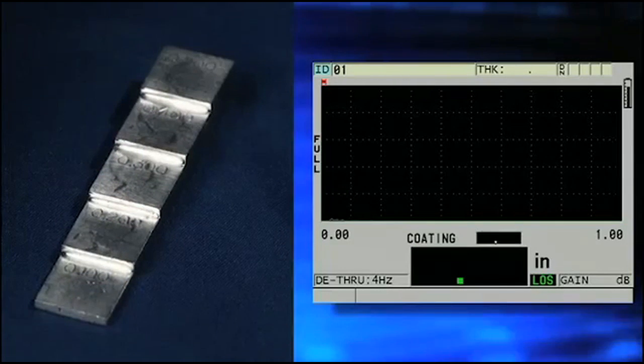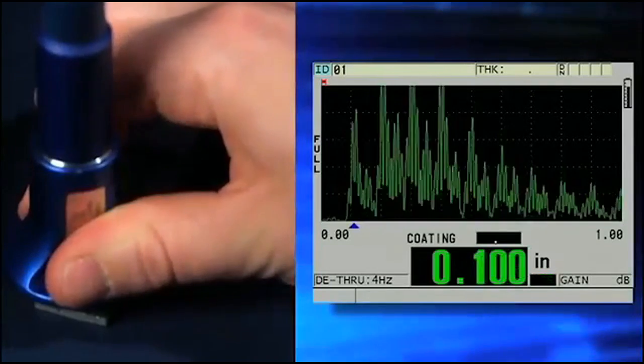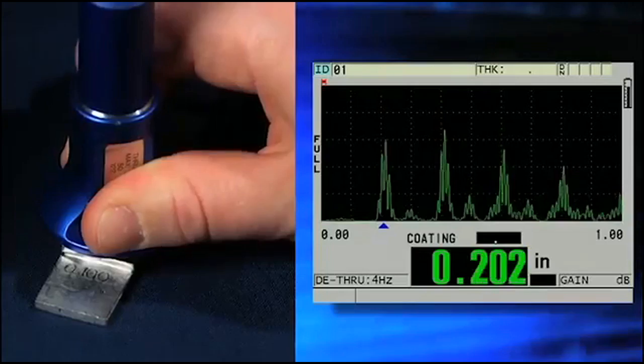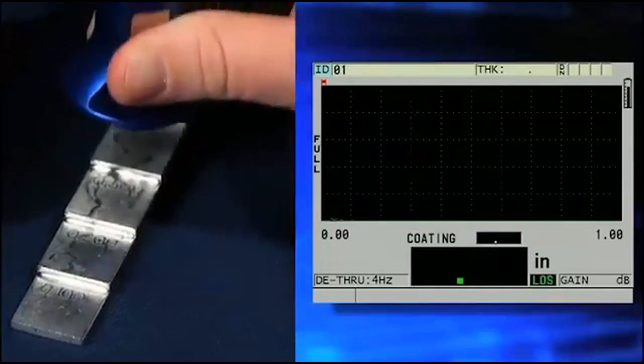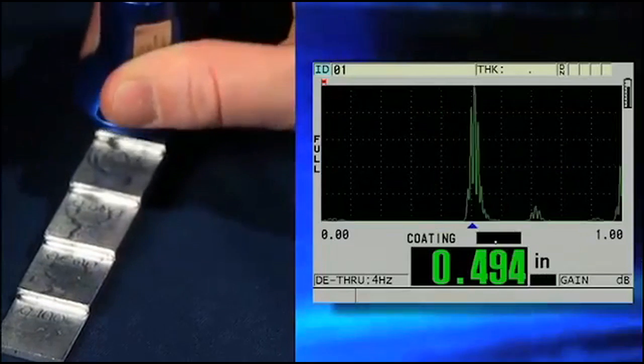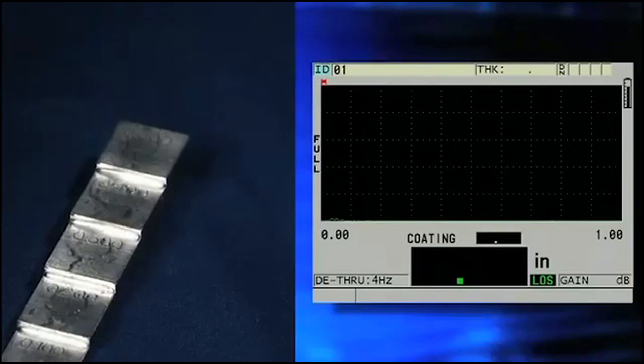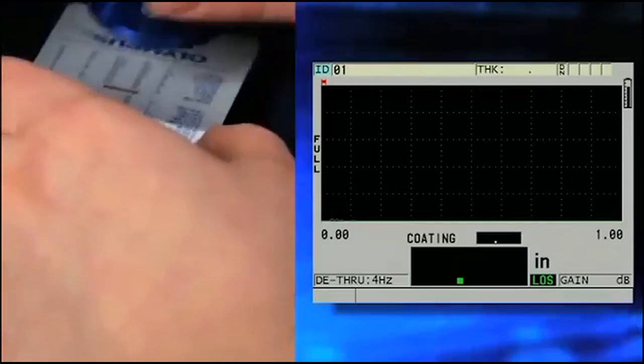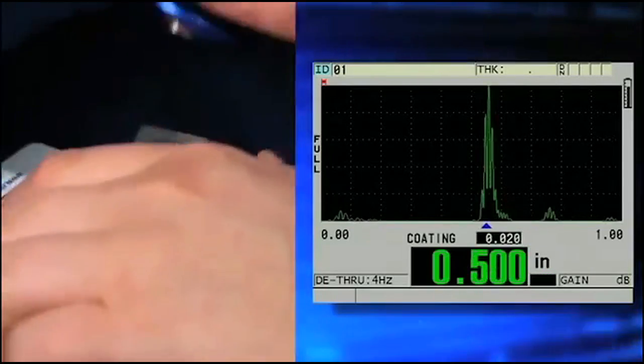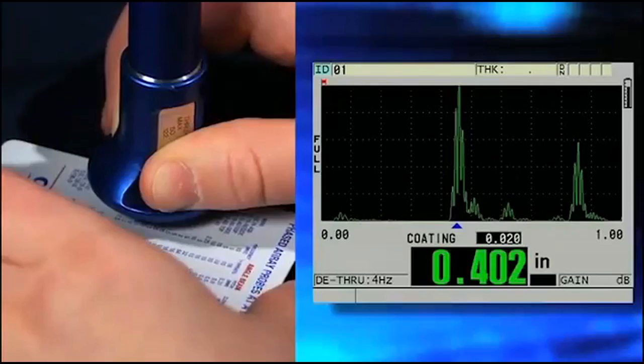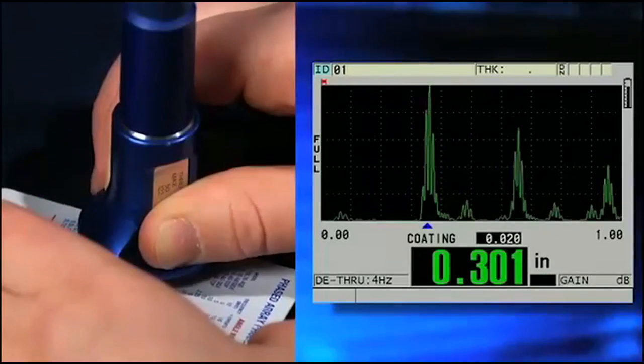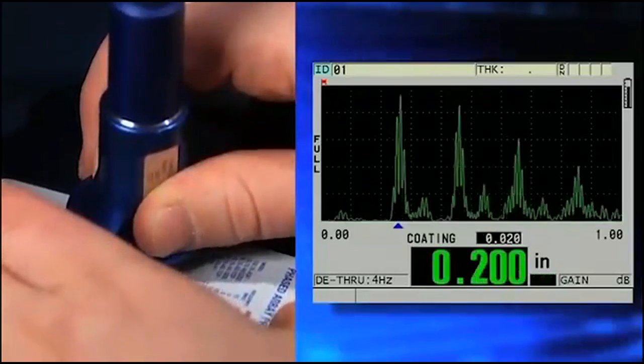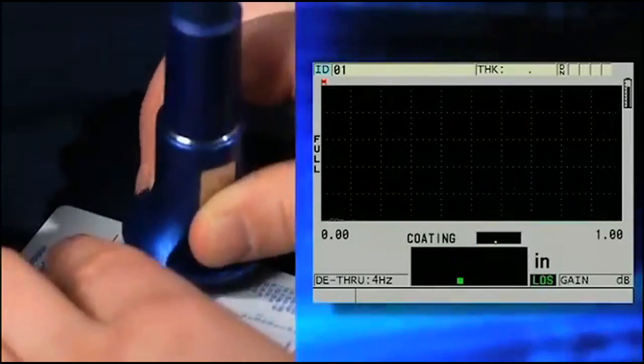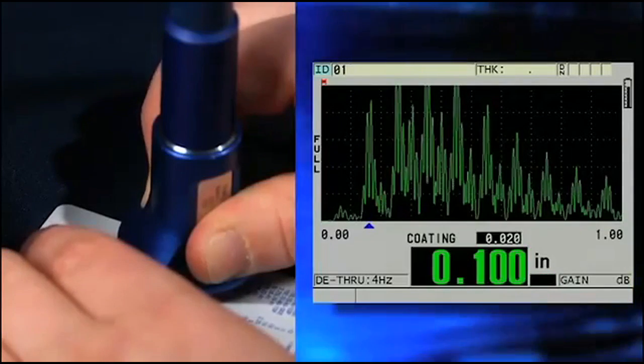We can now go back to the calibration block and check the reference steps: 100 thousandths, 200 thousandths, 300 thousandths, 400 thousandths, 500 thousandths. Now we can go back and check the steps with the coating sample to make sure the measurements are correct. 500 thousandths, 400 thousandths, 300 thousandths, 200 thousandths, 100 thousandths. This completes the calibration for the through-coat feature with the 38DL Plus.